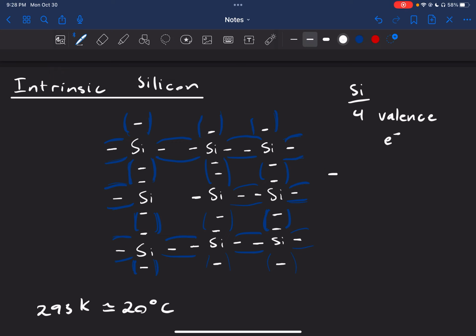And what we're left with is a positive 1 charge in this silicon right here, circled in red. We sometimes refer to that as a hole. We have a hole here, which is the absence of an electron. So now there's the ability for an electron to move to that place. And we'll see that at this temperature, maybe this other covalent bond starts to break as well.